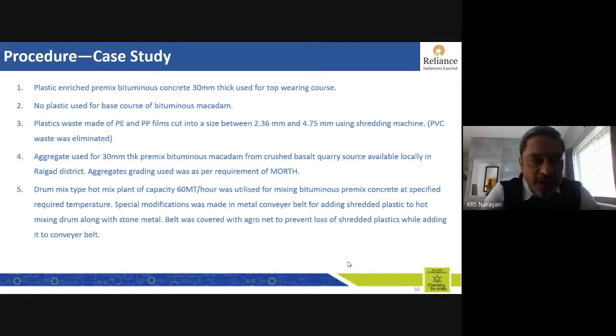So we found that, with our extensive research and knowledge in polymer engineering, PVC was not available in multi-layer plastic. So multi-layer packaging films did not have PVC, very less amount of PET. So we went to analyze the polyethylene and polypropylene inside it, and we shredded to those sizes mentioned. And then whatever PVC waste which was also coming through it was eliminated. That was the external waste which was coming through it.